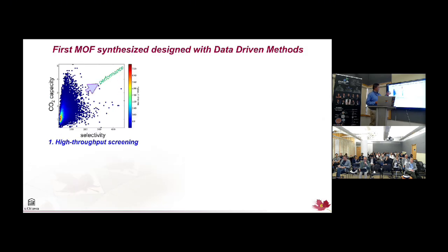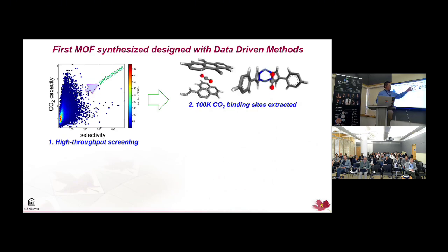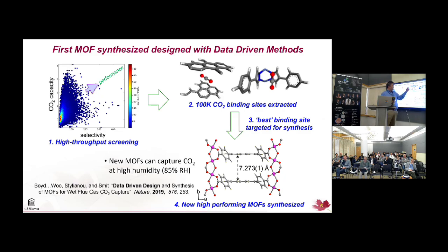So what we did here, we screened a database of about 320,000 MOFs, looked at the high-performing materials with some simple metrics, extracted out the CO2 binding sites, and then did a similarity analysis of about 100,000 of the best binding sites, and then targeted the binding site rather than the whole MOF for synthesis. Our partners were able to make what I call this aromatic sandwich, where we have aromatic rings about 7 angstroms apart. It's good for CO2 capture under wet conditions, and it showed exceptional performance under very high humidity. Usually at those humidities, the water just condenses.